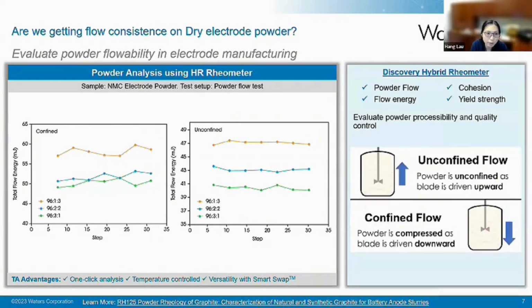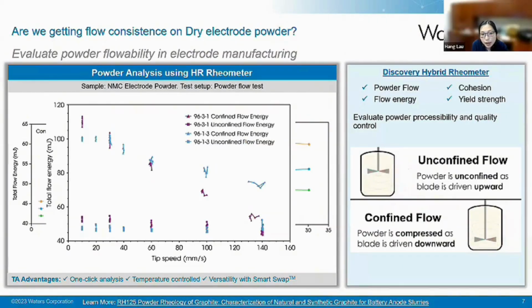Another thing is flowability and flow energy. When you're feeding a mixing tank for pre-dry mixing, it's really important to understand the flowability. There are two types of flowability. We call them unconfined flow and confined flow. Confined flow is when you're actually compacting down and flowing downward. You will see three types of formulation that we're showing here. You can see they are very, very different in flowability and flow energy. The flow energy also depends on the flow speed. When you have a faster flow, you have higher shearing. It's very similar to slurry, but you need to understand the powder characterization of those.